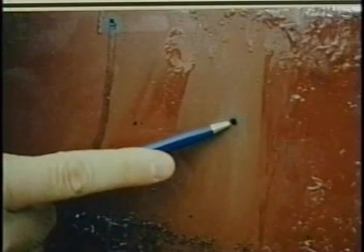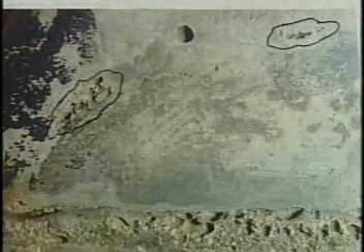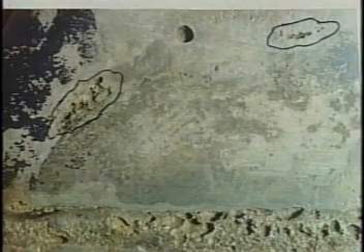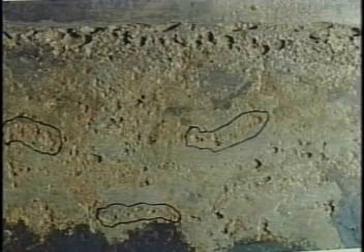I'd like to show you a few photographs of corrosion that has taken place because of bacteria in water-contaminated fuel. Microbes form small colonies that penetrate through the steel plate in perfectly round holes, which are about a quarter or an eighth of an inch in diameter. A closer examination of the bottom plate shows numerous points of pitting corrosion throughout the plate. Each of these pits would eventually develop into a hole in the plate. Once this corrosive water and fuel mixture exits these holes, the attack begins on the steel. In effect, it's now being drilled by the bacteria from both sides.